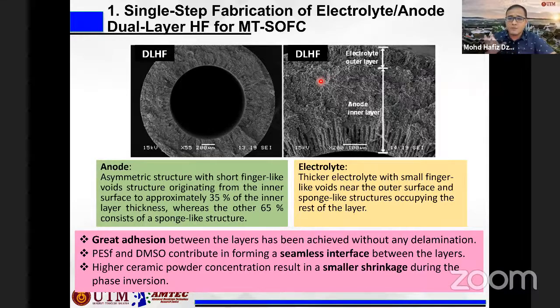The issue with ceramic material, especially for multi-layer, is always associated with delamination, meaning that the inner and outer layers have different thermal expansion, and therefore it can create some cracks. But because we use the same polymer binder and the same solvent, the interface between the layers is seamless, meaning that we cannot see much difference between the electrolyte and anode layer. The electrolyte you can see here is much thinner than the anode layer, and in the anode layer you can find some finger-like voids. That's what we call the asymmetric structure.